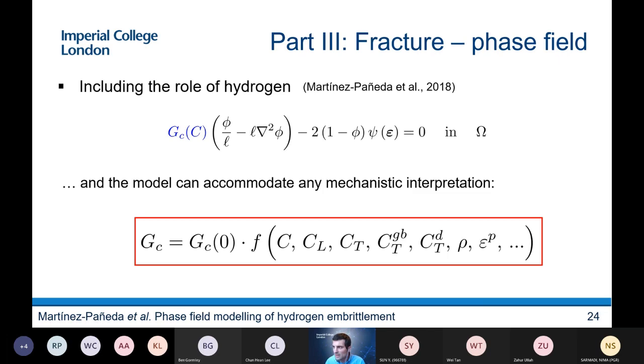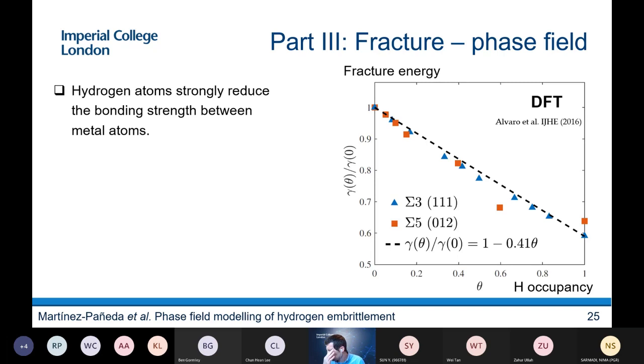The question is, of course, how do you define that dependency, that function, right? And this is good because there's many possibilities that one can exploit. You can make your toughness dependent on the lattice hydrogen concentration, the hydrogen in those traps that I mentioned before, depending on the dislocation density. You can make it depending on any mechanistic interpretation. The logic that we follow is as follows. So we say, first of all, we run offline atomistic simulations. And when we run offline atomistic simulations, what we see is that the fracture energy decreases with hydrogen occupancy. So quantitatively, by running atomistic calculations, we can see how much the fracture energy decreases with the hydrogen occupancy. And actually, what you see here is that if your interface is full of hydrogen, so that's an occupancy of one, you reduce your fracture energy by 40 percent. So that explains why hydrogen is so dangerous for metals.